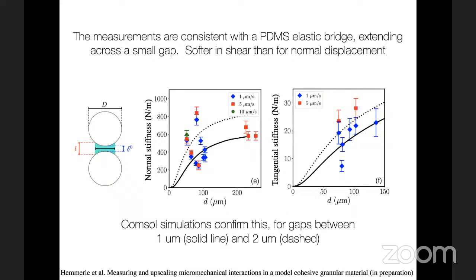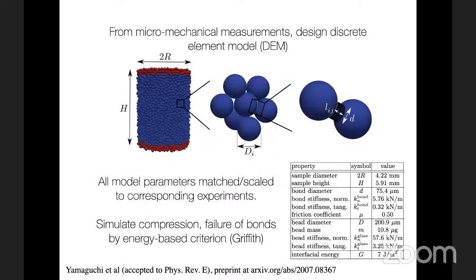So the key result here is that we have a stiffness of the bonds between the particles that we can then give to our numerical model. So the numerical model is a standard discrete element model. We take particles, these are inspired by the models designed for granular materials, except we play with the force law for interacting particles. We have a case where there is a bridge between particles, and we have a case where that bridge is broken.